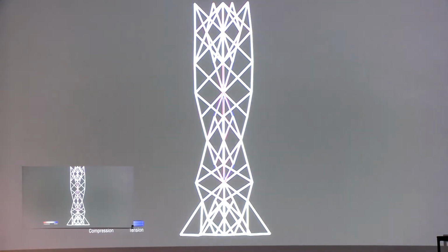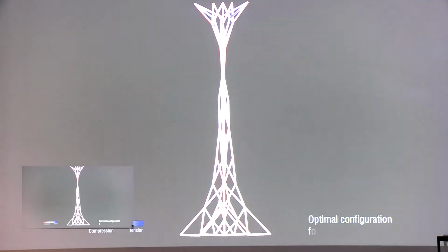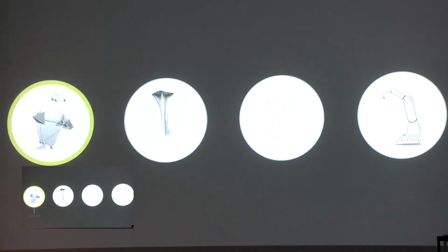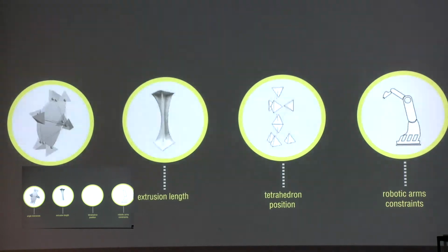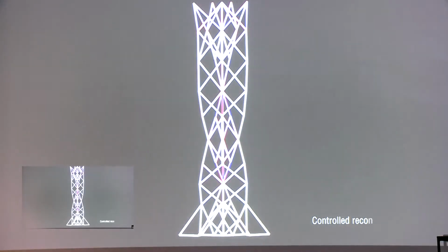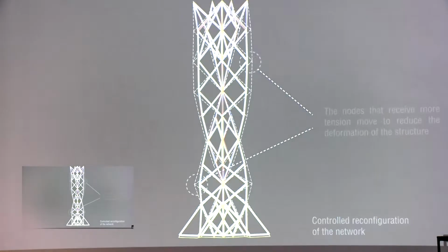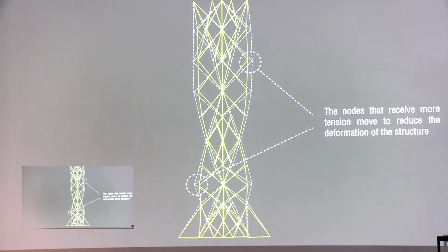So we studied how we can achieve a pure axial network using a particle spring system. But we also need to consider the constraints of our material: angles, extrusion length, tetrahedron position, and robotic fabrication. According to this, we developed a strategy where we control the relaxation of the system, allowing only those points that have more tension to move. So we are trying to reduce the singularities in the flow of the tension.